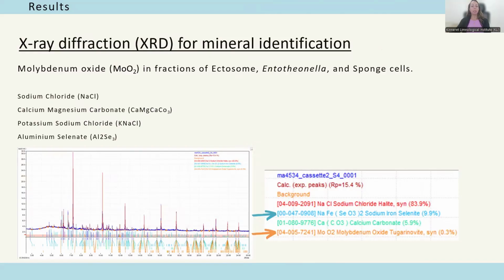To test whether crystalline molybdenum-bearing minerals are present, we continued with X-ray diffraction. We used high-resolution powder X-ray diffraction to look for crystalline phases in the different sponge fractions. The analysis detected crystalline molybdenum oxide in the ectosome, Entotheonella, and sponge cells fractions. Other crystalline phases were also detected, including sodium chloride, calcium magnesium carbonate, potassium sodium chloride, and aluminium selenate.